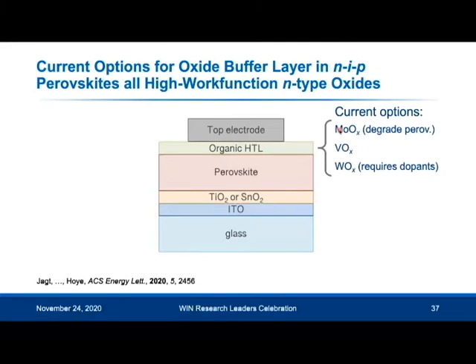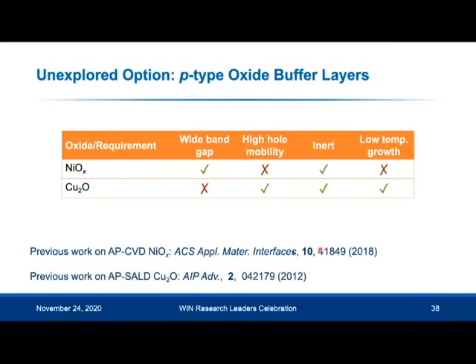So we want to look at alternatives, so why not look at a stable P-type oxide as an alternative to these high work function N-type oxides. And when we did this work, people hadn't looked into these P-type oxide buffer layers before, so we looked towards what oxides were used as hole transport layers beneath PIN structured perovskites. And the two most common hole transport layers used are nickel oxide and Cu2O.